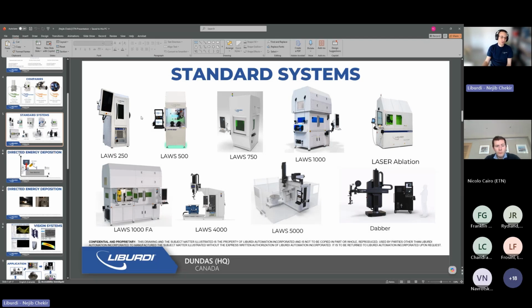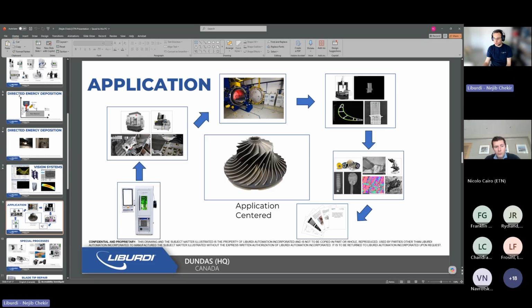You can then add more advanced characterization techniques to understand anything from dilution to the different phases that can develop in the deposited weld, and you can also use CMMs or X-rays to validate that. Once the weld development is complete, typically you have a weld schedule and the parameters are locked. The combination of calibration and verifications on the machine, anywhere from weekly to monthly to every 6 months, will ensure that your machine produces a repeatable weld in the area of interest.